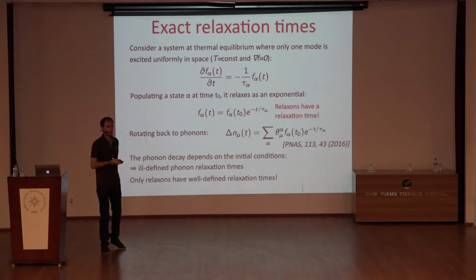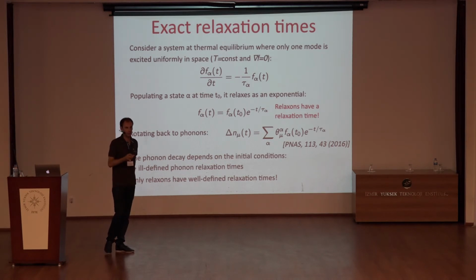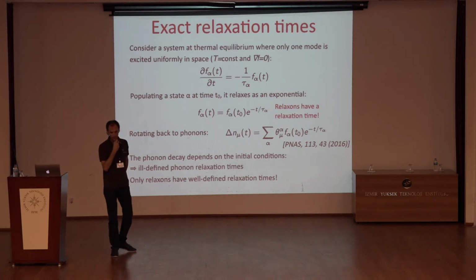So you could decide to build them in such a way that this phonon state in one case will have a positive relaxation time, in another case will be negative, and then you can tune in between all the values you want, while these eigenvalues are still uniquely defined as eigenvalues of the matrix. It's tricky.